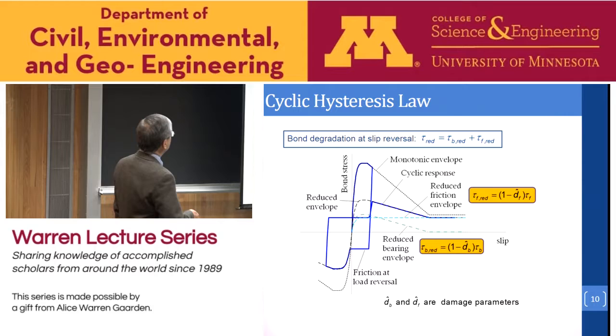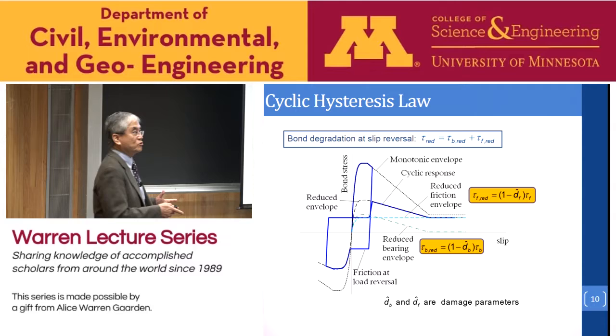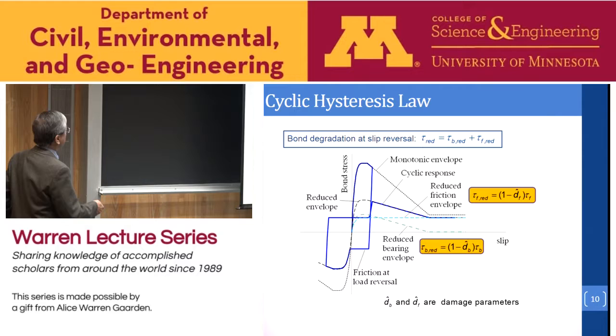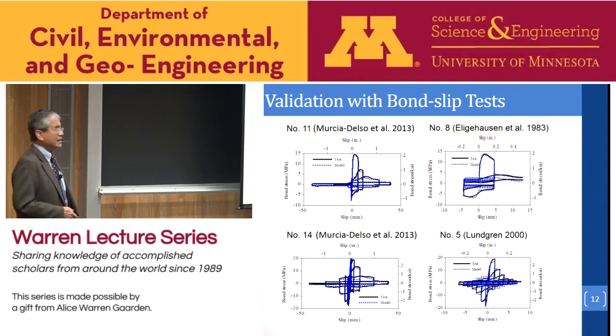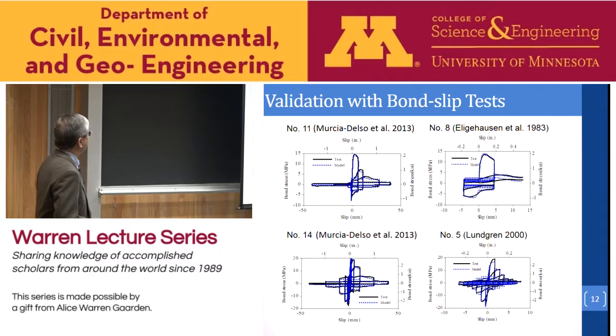DF and DB. So this is related to the degradation of bond strength provided by friction, and this is the degradation of the bond strength provided by the bearing force. So now, after implementing this, we can validate with the bond slip test data we obtained for large diameter bars as well as the test data of other investigators. So we can see that with these tests with different load histories, okay, with different bar sizes, the model actually worked quite well looking at the local bond stress bond slip behavior.